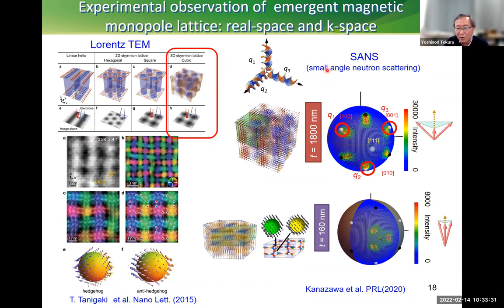The other one is small-angle neutron scattering, right? We shine neutrons on the crystals along the 111 direction. We prepared a very thick manganese germanide film, gathering more than 10 films, and performed the neutron scattering. Then we have very nice three spots along the 111 direction. Each three-spot is a pair. This is due to some chiral domain issues: there are two chiral domains showing up as a pair.